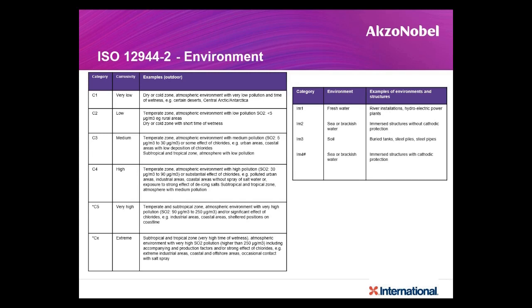Then IM4 is immersion in sea or brackish water with cathodic protection. For example, immersed pipelines, subsea pipelines. It is in seawater, and at the same time, they are provided cathodic protection. That is IM4. So if you look at C1 as the lowest level of corrosion possibility, IM4 has the most intense level of corrosion possibility. Based on this and durability, you recommend coating thicknesses.